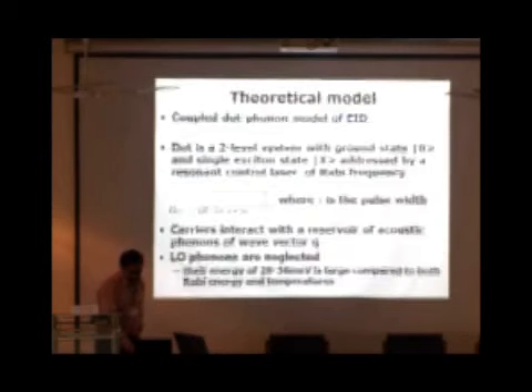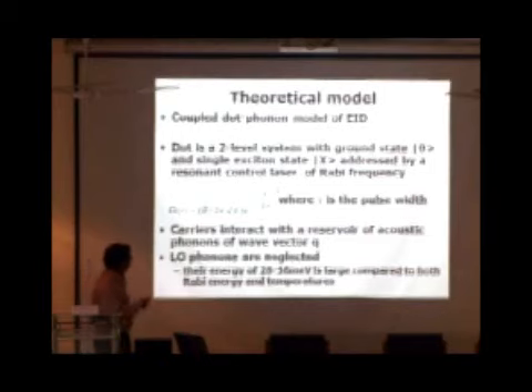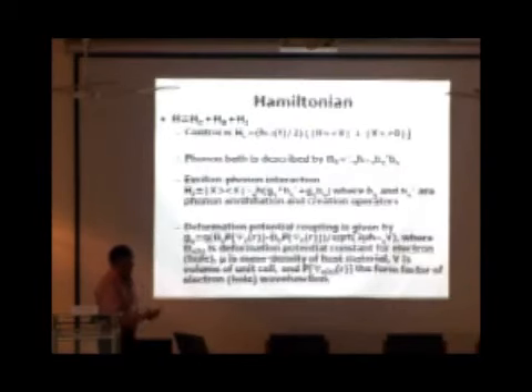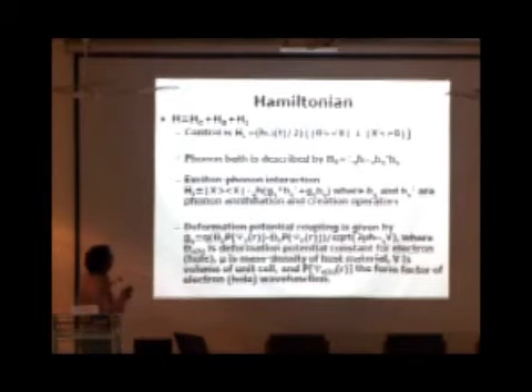Towards this, a theoretical model has been developed. Look essentially at the Rabi frequency. We assume the excited carriers interact with a reservoir of acoustic phonons, and LO phonons are much higher in energy, so we ignore them. A Hamiltonian has been written which has three components: one is the control, the second is the phonon bath, and then the interaction term.